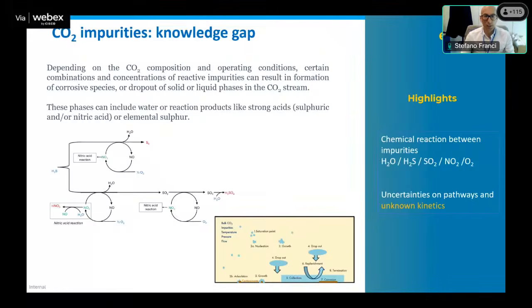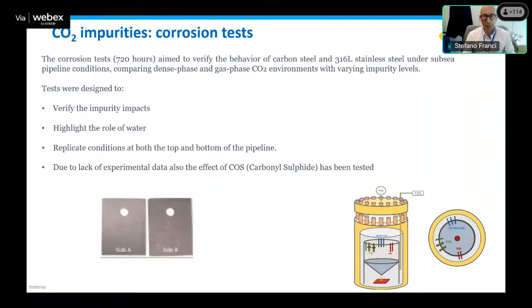And as already mentioned, the species which are the 5 bad boys, and we look at during our testing campaign are the 5 highlighted on the right-hand side: water, H2S, SO2, NO2, and oxygen. And we performed some tests in order to detect any acid formation and eventual dropping out and corrosion issues. So the initial setup for the testing is an autoclave. You can see on the right-hand side some coupons hung on the top, some on the bottom.